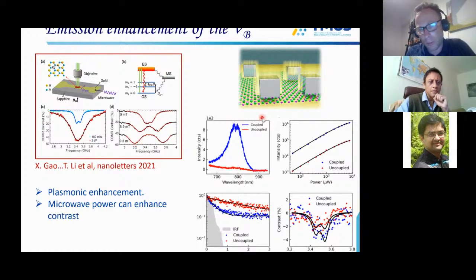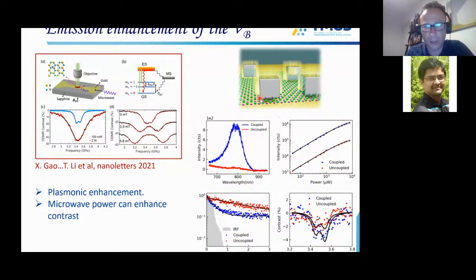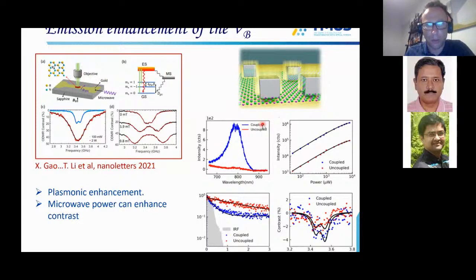And ourselves, we also tried a gap plasmonic cavity to enhance the emission, and we managed to increase it by a factor of 10. Not as much as these typical gap cavities should give you. So the expectation here is to really go to about a factor of 100 or so.